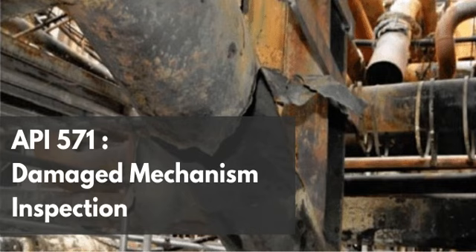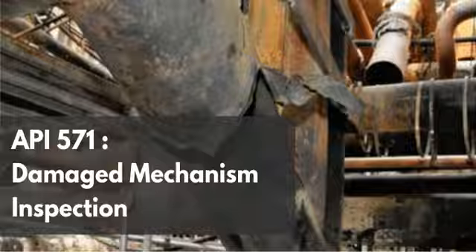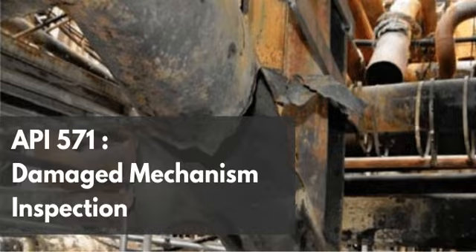A crack in a high-stress line often means you might have to shut the unit down immediately, initiate emergency procedures, and prepare for a major mechanical repair. But if it's actually localized corrosion, if it's just a deep groove. If it is corrosion, your engineering assessment is based on entirely different principles. You are looking at remaining wall thickness, general corrosion rates, and calculating the burst pressure of the remaining metal. It requires a completely different response. So it's not a fracture risk in the same way.